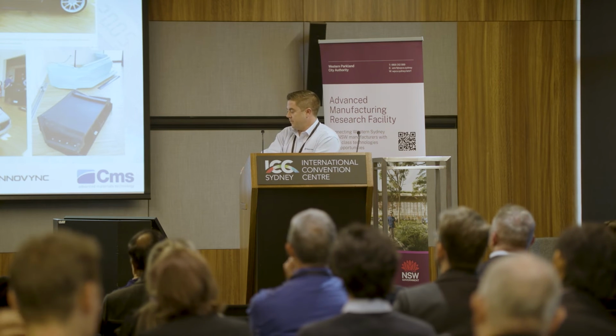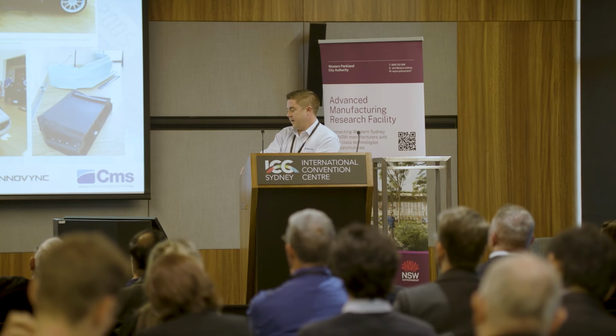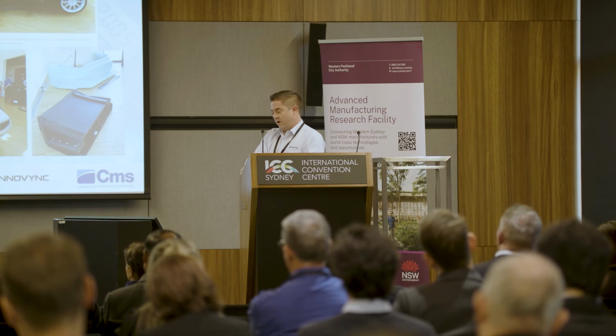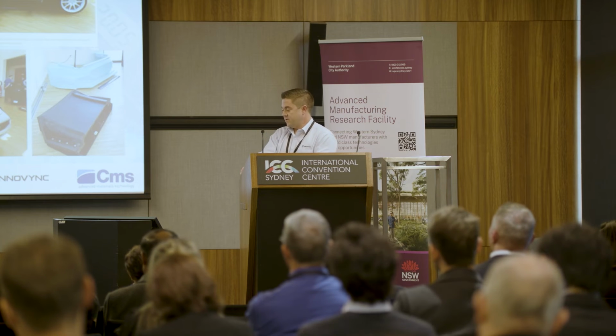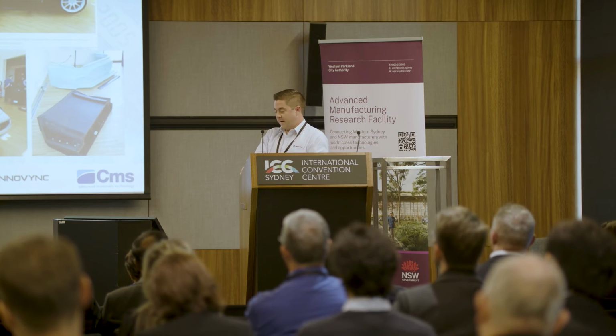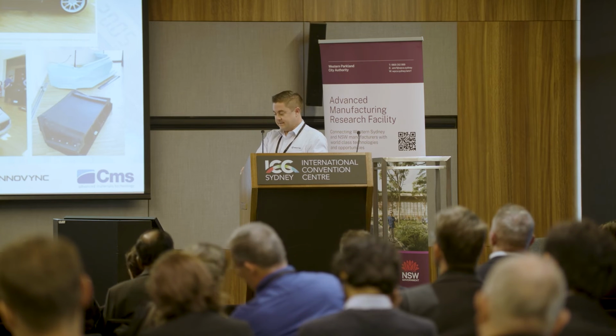reimagining them with a wider and more modern design. Each component was built from a carbon fibre prepreg, manufactured via hand layup on a 3D printed mould, then cured via autoclave. Using the CMS Creator, 20 individual moulds were printed using a 40% carbon fibre filled PA6.